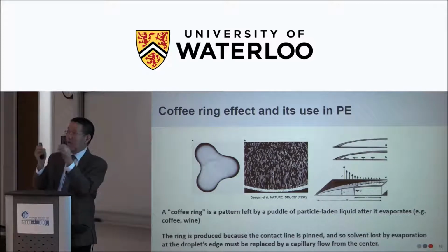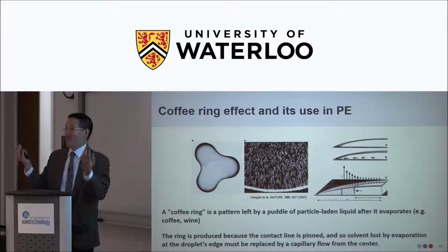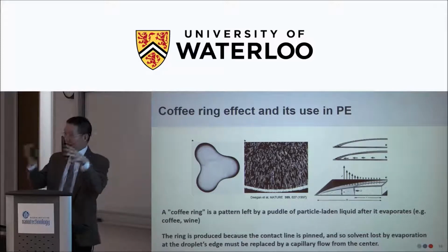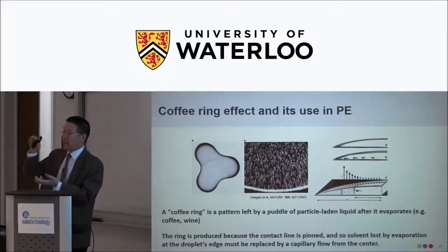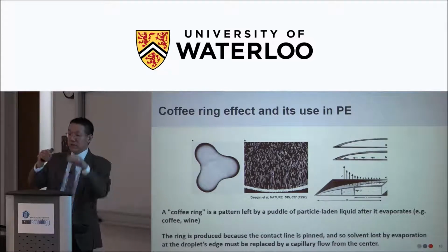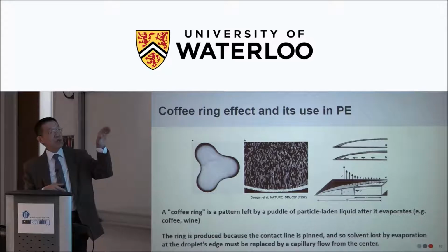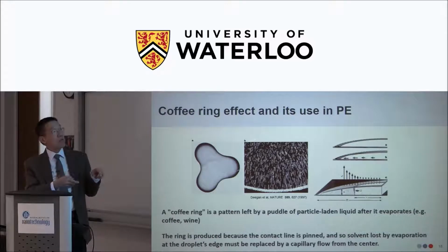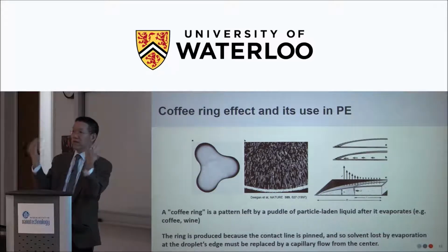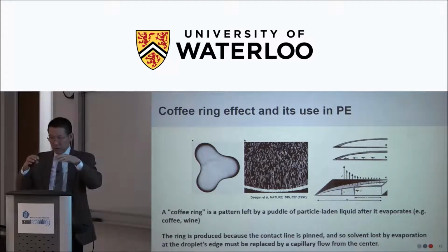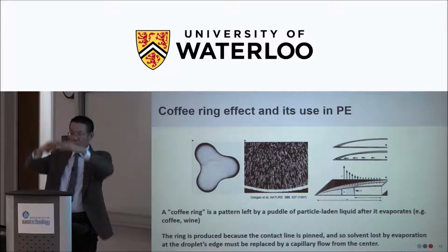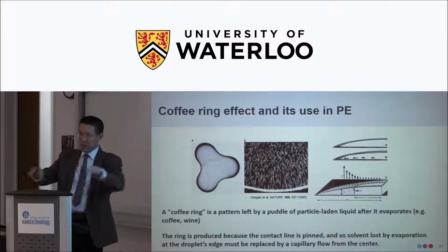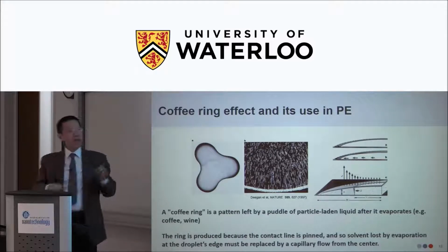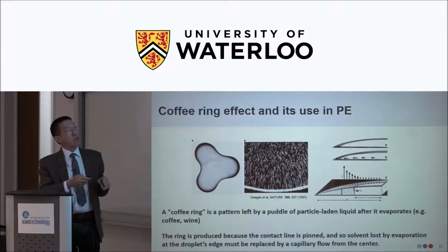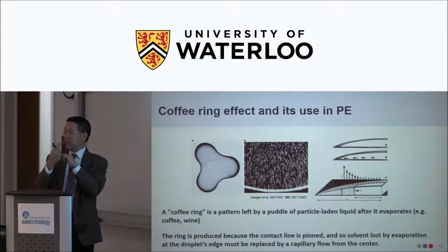So all the coffee nanoparticles, micrometer particles, migrate to the edge. Because when a drop of ink wets the surface, the three-phase interface, the air, substrate, and the liquid, that area dries up first. It pins the interface. And when the liquid dries up, the dome structure pushes down. You have a capillary effect to push these particles towards the boundary. So by the end, all the particles are around the boundary, and that's why you see a stain ring called the coffee ring.